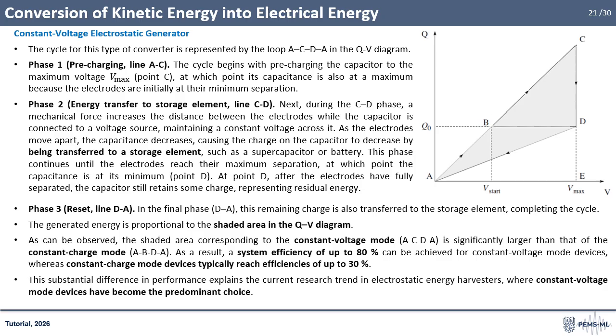Phase 3 is reset, corresponding to line DA. In this final phase, this remaining charge is also transferred to the storage element, completing the cycle. The generated energy is proportional to the shaded area in the QV diagram. The area corresponding to the constant voltage mode, ACDA, is significantly larger than that of the constant charge mode, ABDA, enabling system efficiencies of up to 80% for constant voltage devices, compared to about 30% for constant charge devices. This performance advantage explains why constant voltage operation dominates current electrostatic energy harvester research.